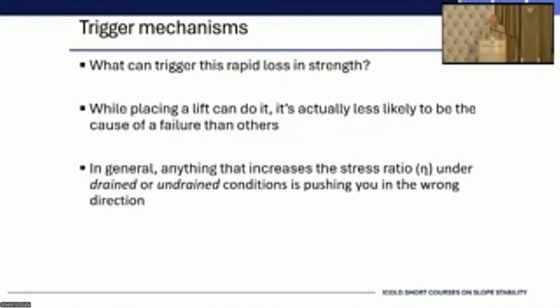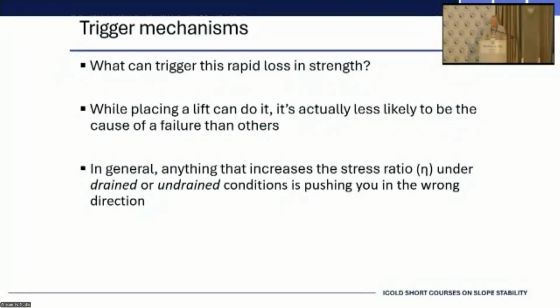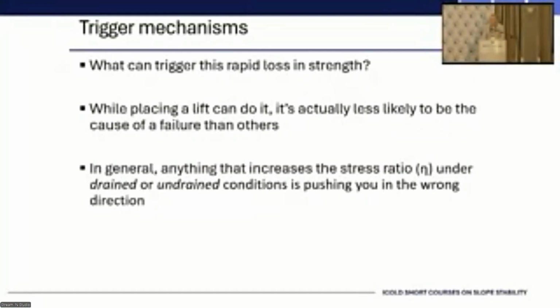Now, that's one mechanism. What else can trigger it? Well, perhaps placing a substantial new lift of tailings very rapidly is potential because it's increasing your shear stress quite rapidly. It's probably less likely to be a cause. I don't think we've seen too many triggered by lift, but maybe it can't be completely discarded. But anything that increases the shear stress ratio under either undrained or drained conditions is pushing us in the wrong direction. It's pushing us close to that instability stress ratio. And just to emphasize the point made yesterday, you can load it under purely drained conditions up to a point that's very close to, or even sometimes beyond that instability line. But then when failure gets triggered, failure being this runaway generation of excess pore pressures, then you get this really dramatic loss in strength.